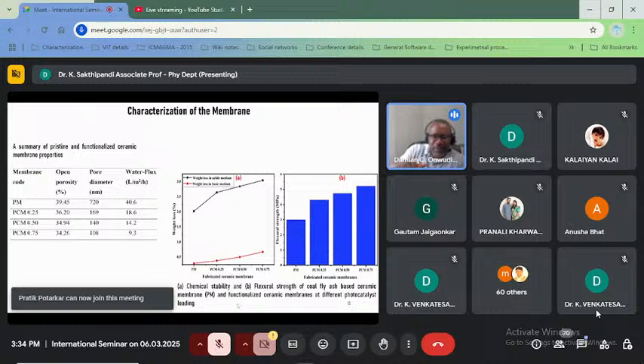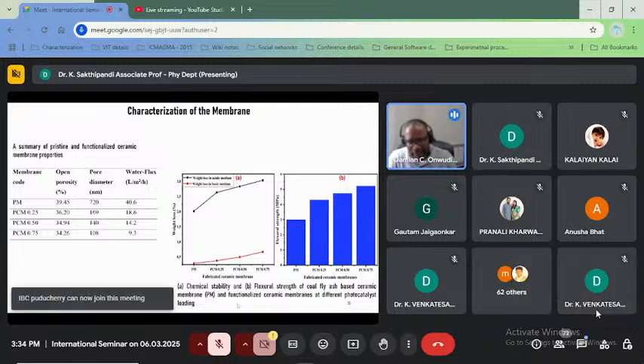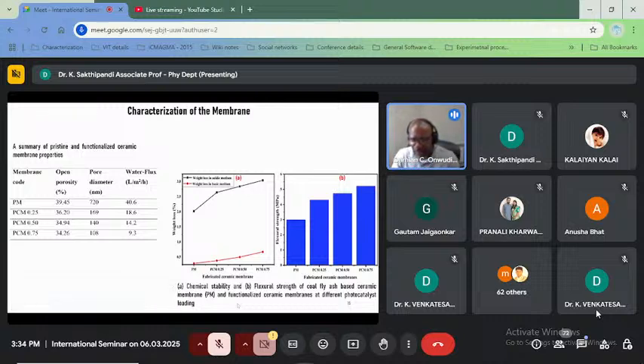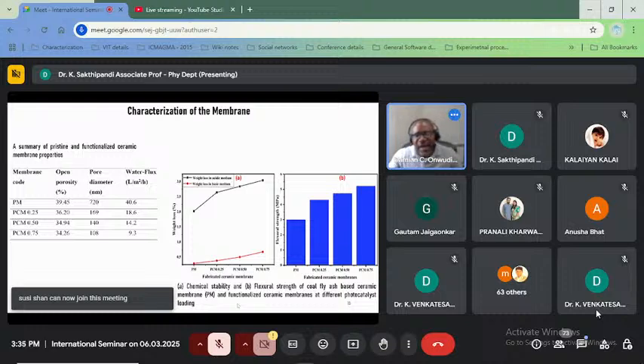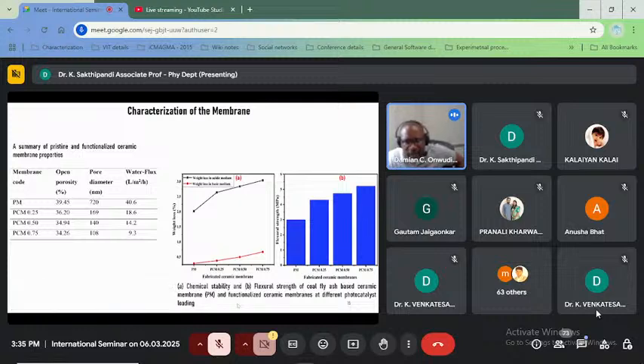Then the pore diameter also decreased, and the amount of water that could pass through it also decreased, because as the pore diameter decreased, the retention capacity increased, and the amount of water that could go through it decreased. And this also impacts the ability of the material to filter water. So what we now needed to do was to balance between the two.